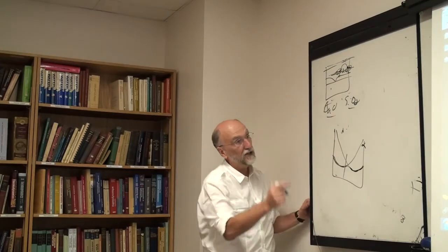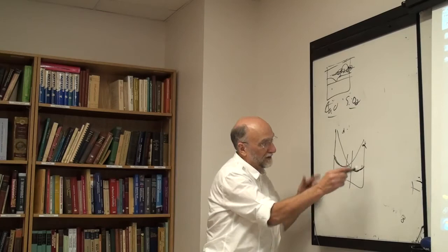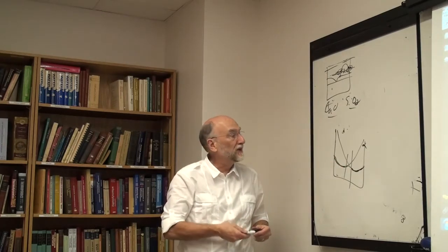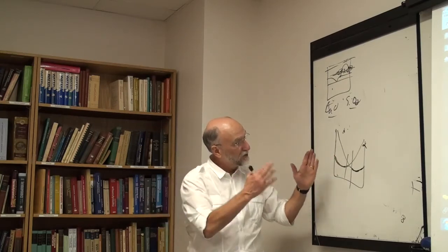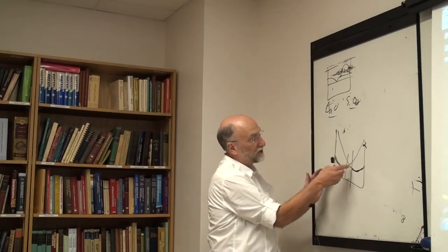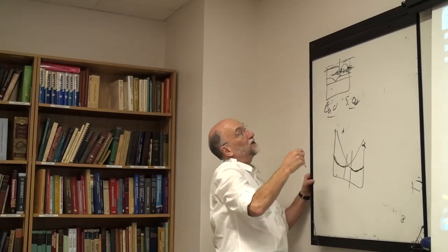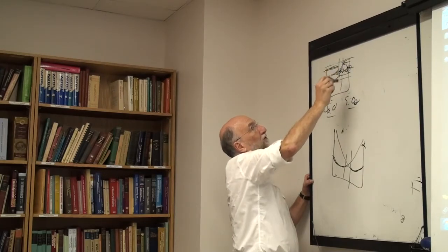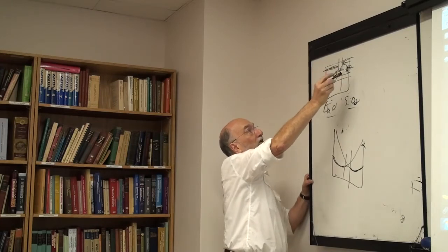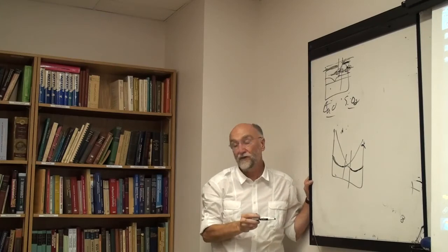So treating this as the dilute solution model, and treating this as the dilute solution model, is pretty good in the terminal region, because that reflects more what's going on in the solution. The solution really does have two terminal regions with very different structures, and a central region where the two structures have to come together somehow. So fitting this region up to 70% silica with one model, and fitting it going the other way from 100 to 80% silica with another model, gives you a very simple fit here, and this model would give you a very simple fit over here.